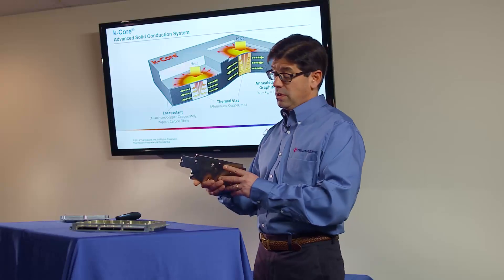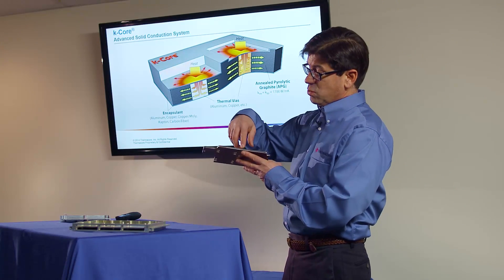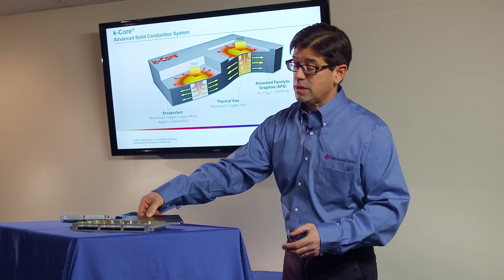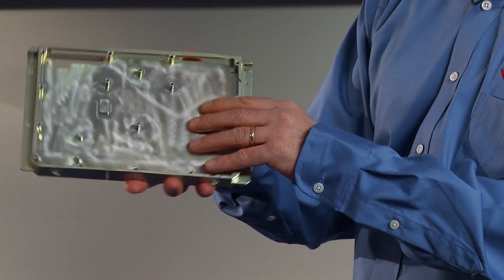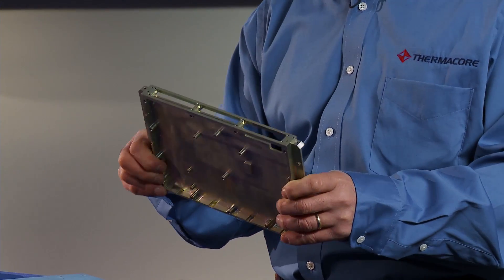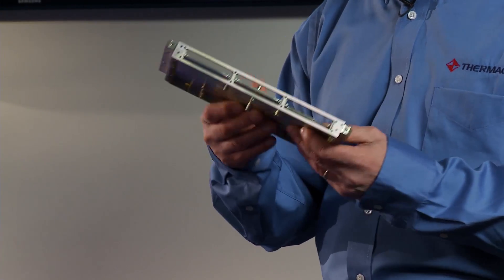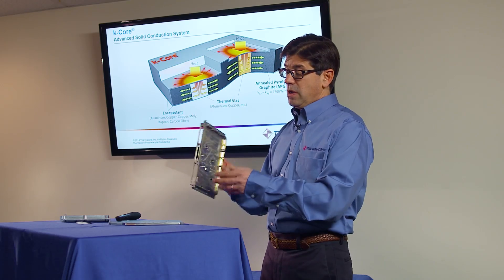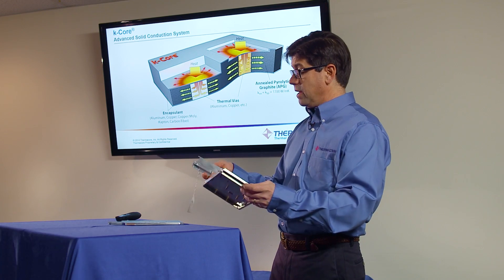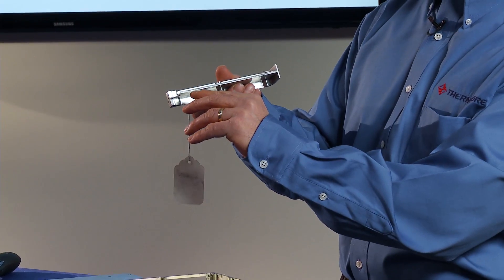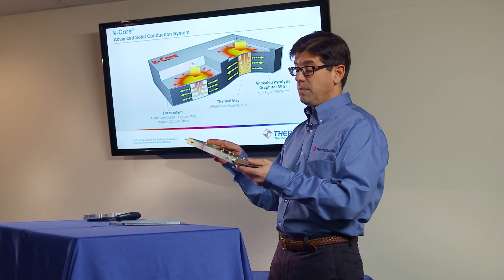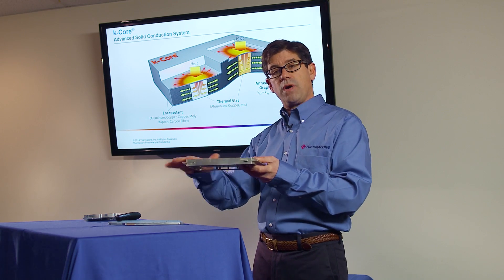Some features of this material include applications where we put solid metal regions to provide through-thickness conductance. Some of the more complex designs are machined elements which are laminated in a thicker format and machined back. Any kind of aluminum part typically used now can be replaced with a K-Core type part with much improved thermal conductance. This particular part has a middle plane about 100 mils thick, containing an annealed pyrolytic graphite insert about 60 mils thick — a good volume fraction providing that highly conductive path.